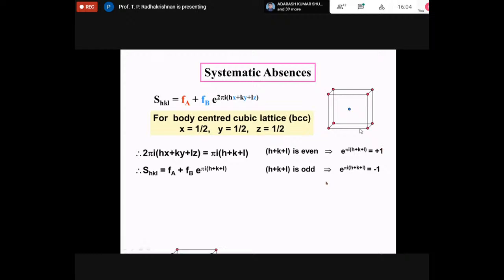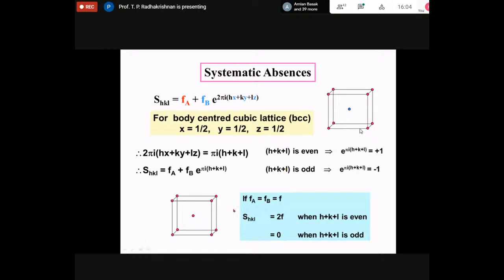Now, what is the consequence of that? Please remember, as I mentioned, this blue atom is actually a red atom. So I put these two different only to write this equation initially. So Fa and Fb are equal. That is what it means. Both are same atoms, means both have same atomic scattering factor, F. If I put F as a common factor, this equation will become F into 1 plus e to the power i pi into H plus K plus L. Depending on whether H plus K plus L is even, that will be plus 1. So it will be 1 plus 1 in the bracket. It will become 2F. If it is odd, it will become 1 minus 1 in the bracket. So it will become 0.